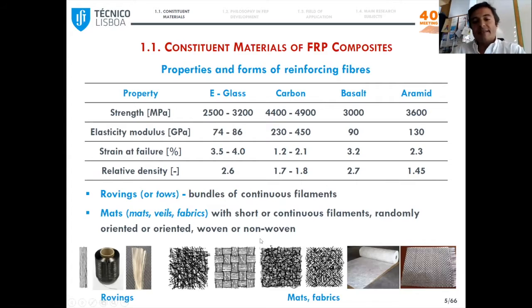Here I listed the 4 types of fibers most often used in FRPs: glass, carbon, basalt, and aramid. They are available as rovings with continuous fibers, or mats, which can have short or continuous fibers with different orientations and patterns. In this table, you can see that all fibers have very high strength, and the most relevant difference between them is the modulus, which is maximum with carbon and minimum with E-glass.